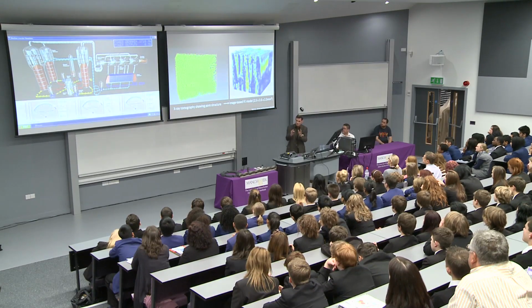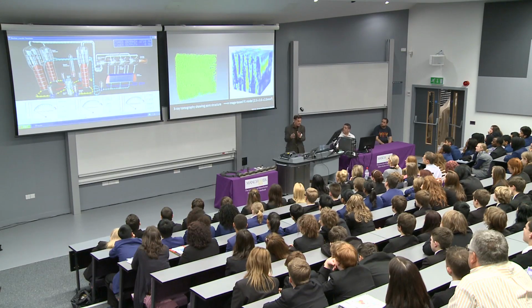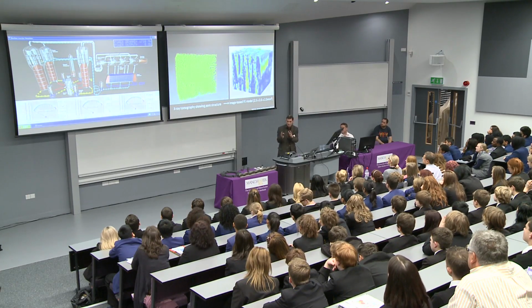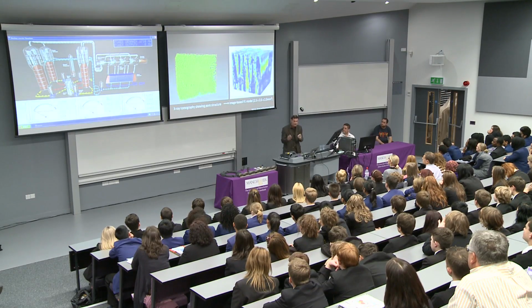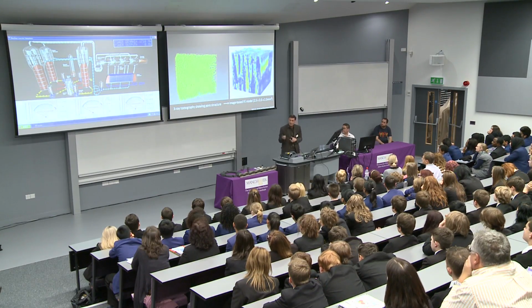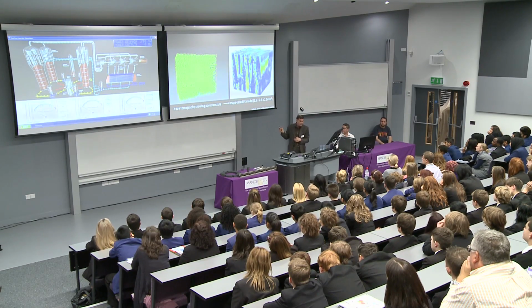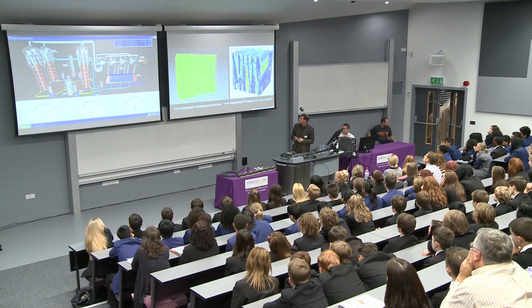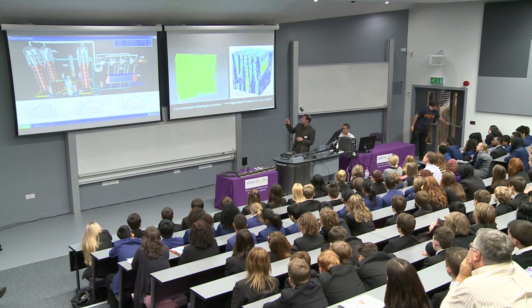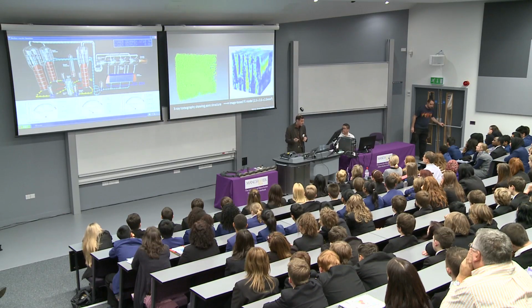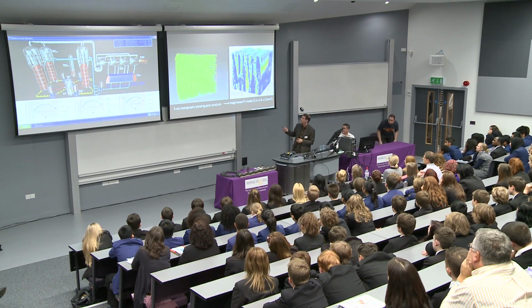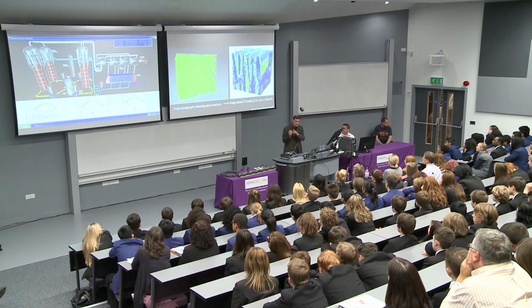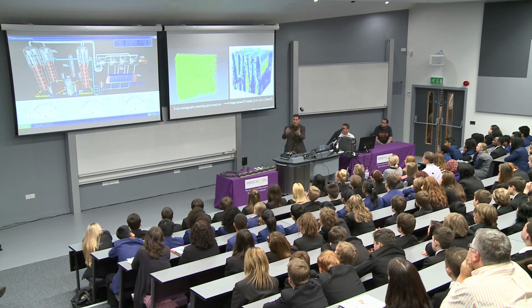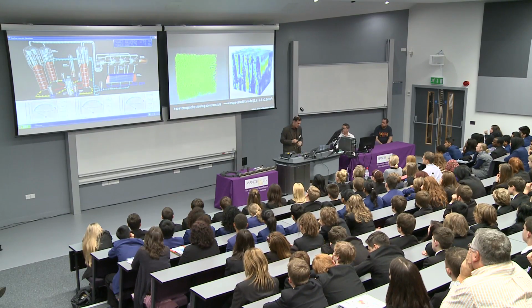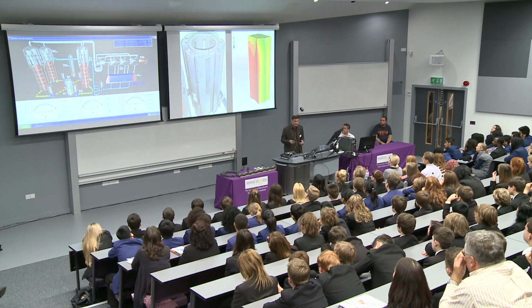That enables us then to take that information and build it into a computer model of the graphite where we can actually calculate how that graphite material will behave at temperature and under stress. And what you can see in this diagram is what's called finite element analysis. So this is a computer simulation of the graphite. And this shows the state of stress within the graphite block. So you can see the stress isn't uniform. It's affected by the microstructure. Well, that little bit of information can then be fed into larger models to predict how the larger brick will behave over time. And that's what this simulation shows.